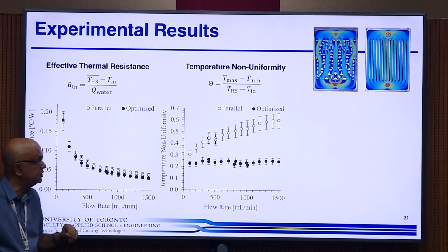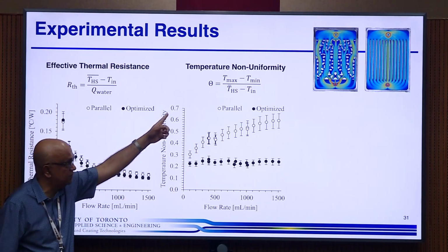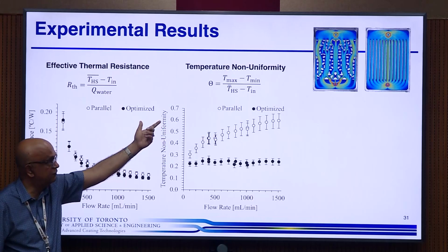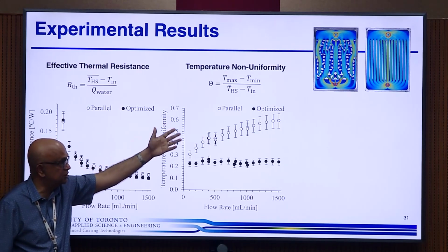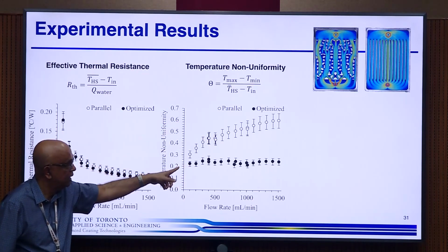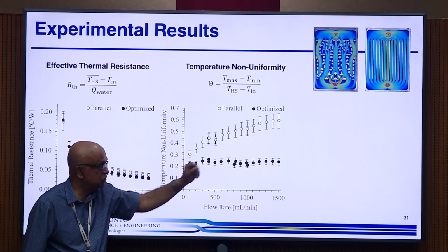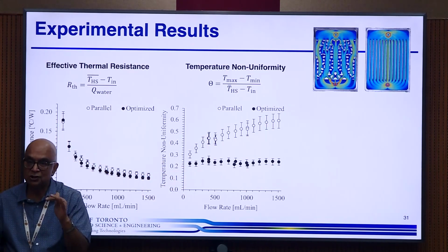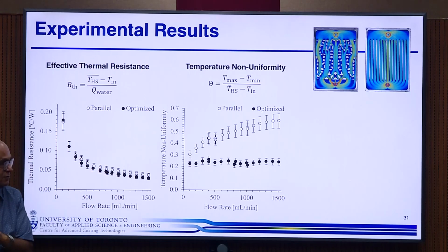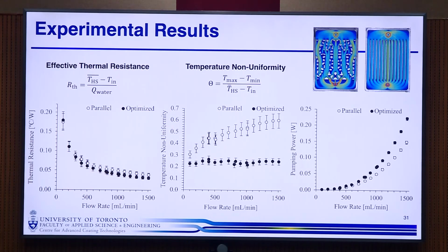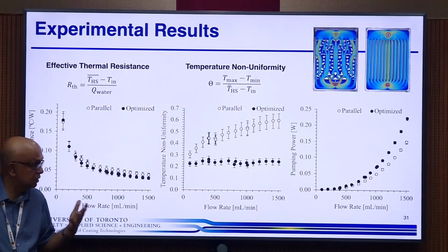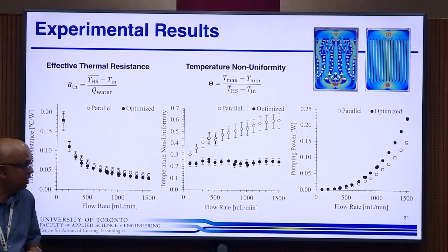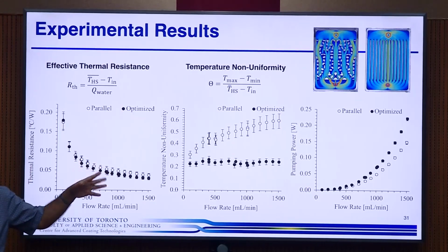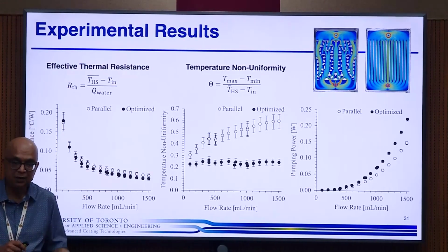This is what we define as the temperature non-uniformity. So it's the maximum minus the minimum, and we've normalized it by the heat sink temperature minus the water temperature. And this is much lower for optimized, and it stays constant independent of the flow rate. And the price we pay for that is slightly greater pumping power, but this is so much smaller than the power that we're moving that we don't really worry about it.